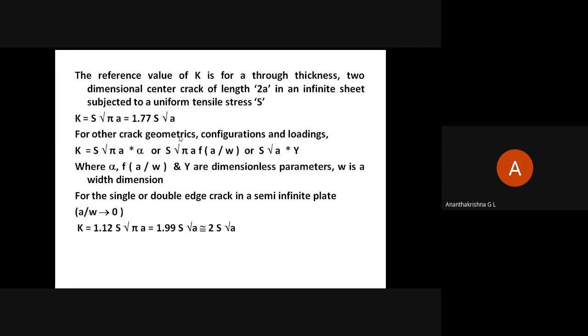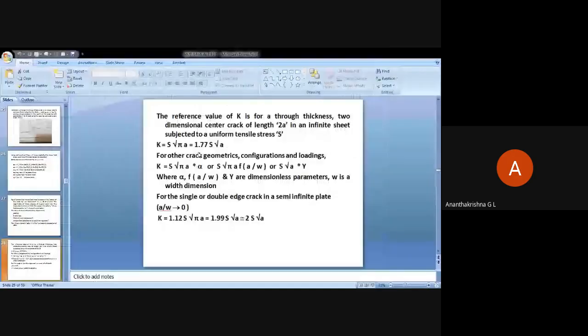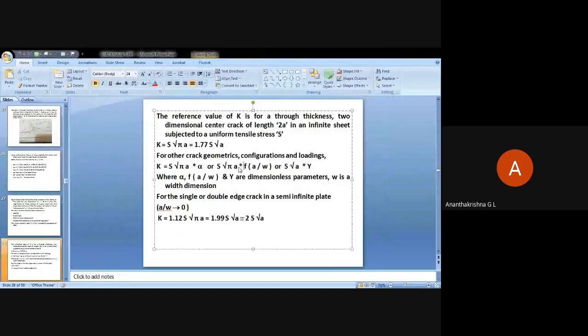For other crack geometries, configurations and loadings, we can have K equal to stress into root pi a into alpha, or S root pi a into F of a by W, or S root a into Y. We can use any of these equations, where alpha, F of a by W and Y are the geometry factors.